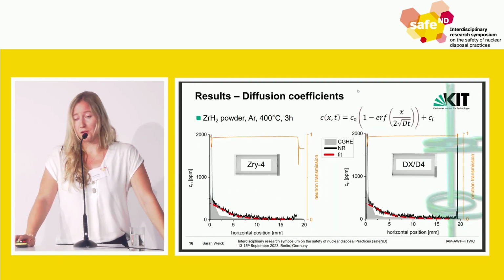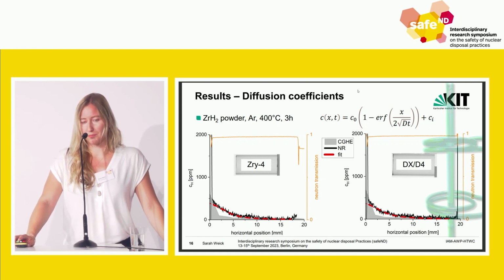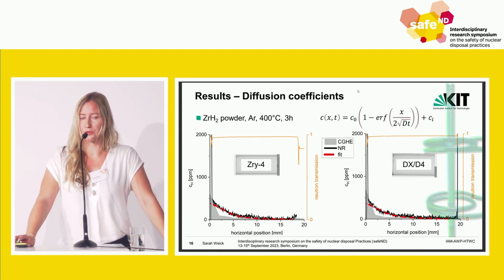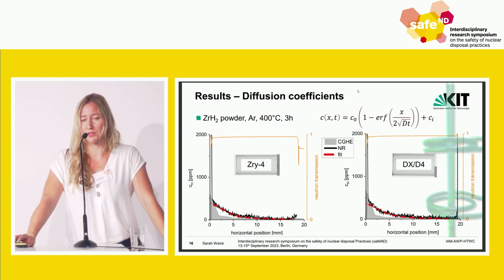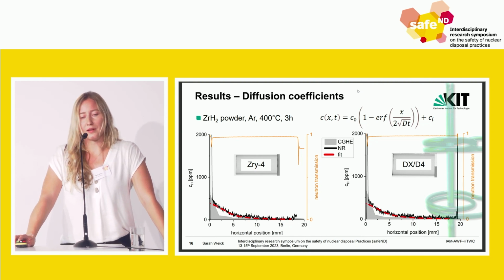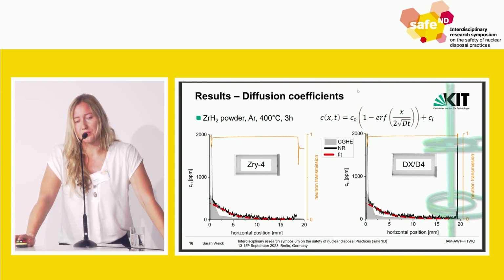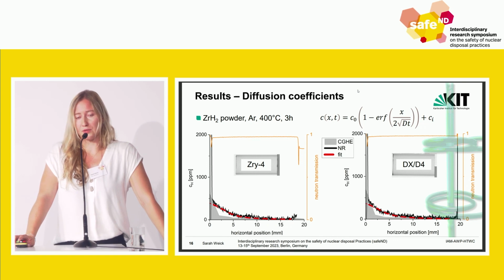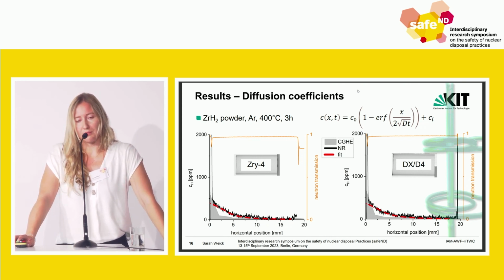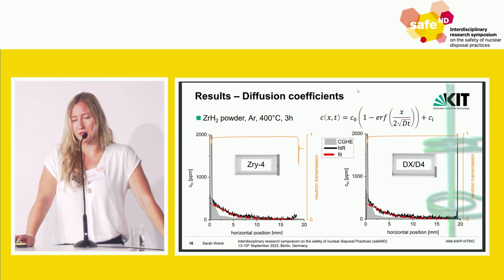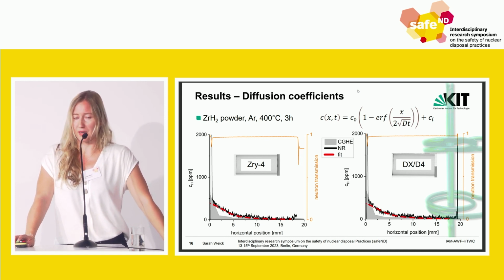To show you some results, this would be, for example, a Zircaloy-4 cladding tube on the left that was hydrated with zirconium hydride powder. So we tried to image how the hydrogen diffuses into the material. You'd see that, of course, the duplex material would behave quite the same, since it's the same bulk material.